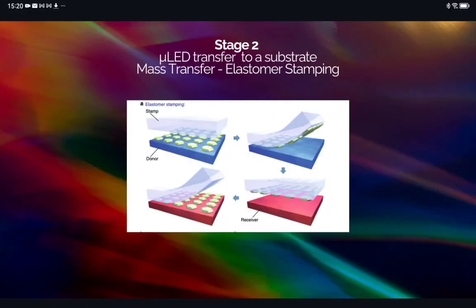Several approaches have been evaluated to massively assemble micro-LEDs, including elastomer stamping, electrostatic transfer, electromagnetic transfer, laser-assisted transfer, and fluid self-assembly. Let's discuss the first method, elastomer stamp micro transfer printing technology, in which devices are transferred by an elastomer stamp utilizing van der Waals force of polydimethylsiloxane. The typical elastomer stamping technique could manipulate micro-LEDs at a high transfer yield of 99.99%, while it typically delivers a processing speed of 10,000 to 25,000 microchips per hour.